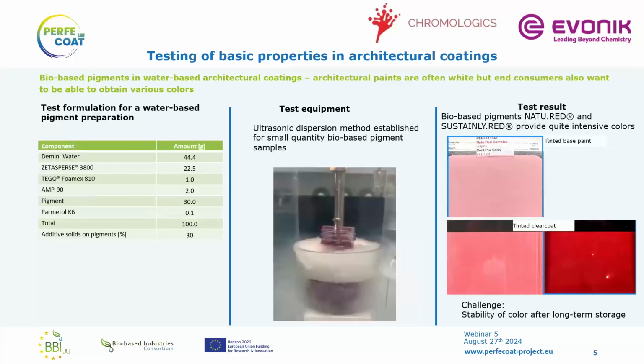I'm going to switch to the next data set. This time we are looking at pigment that we obtained with the support of Chromologics, and we tested in our lab. The function of the pigment we've described already in the earlier webinars is mainly giving color strength to a coating and also remaining stable in time. Those are the two main performances we expect when using pigment.